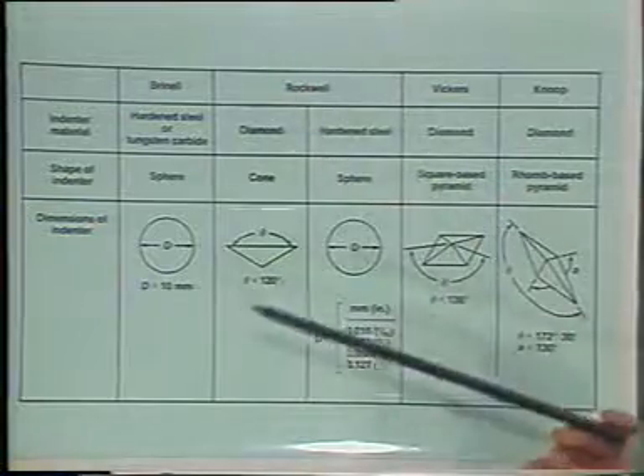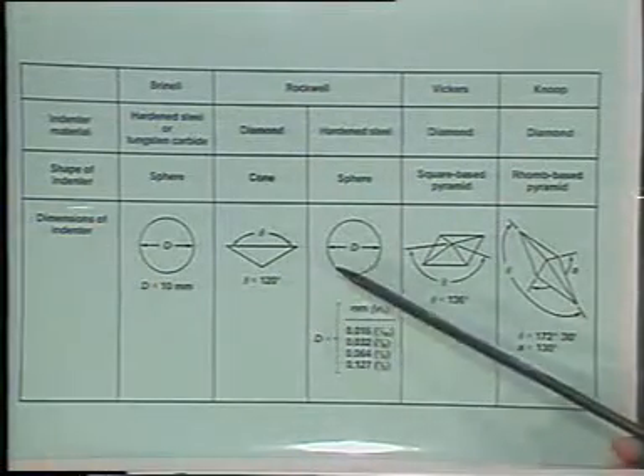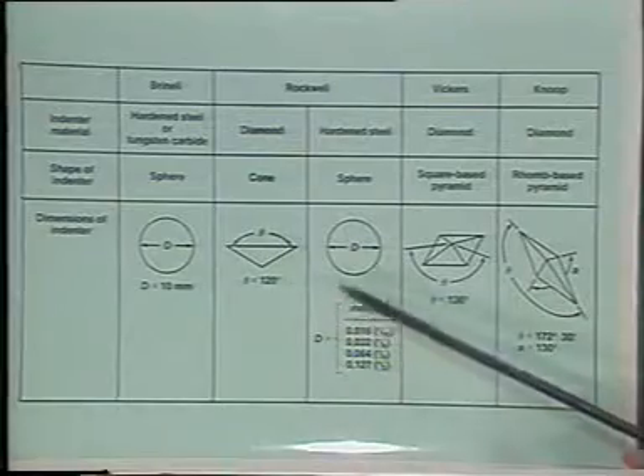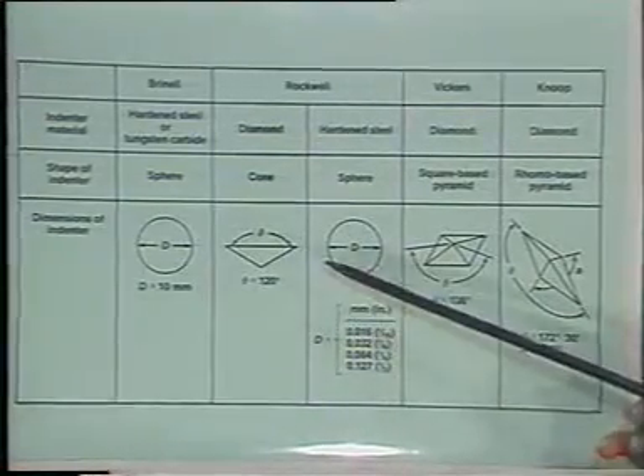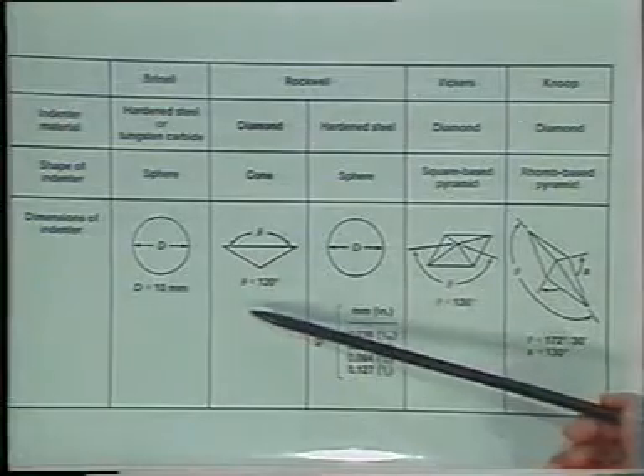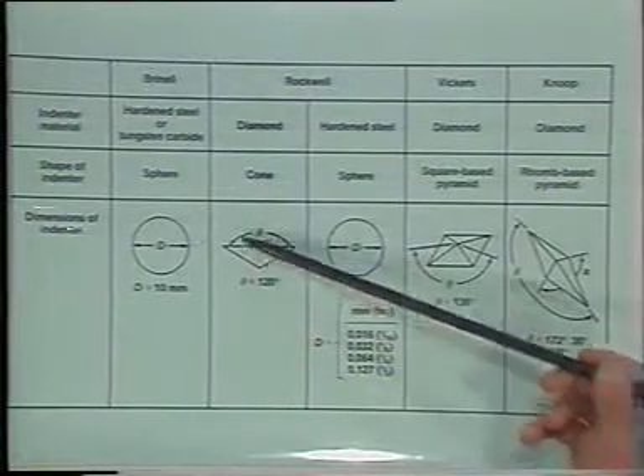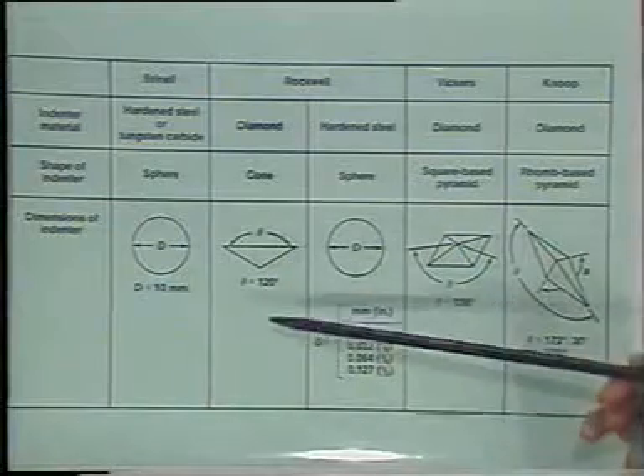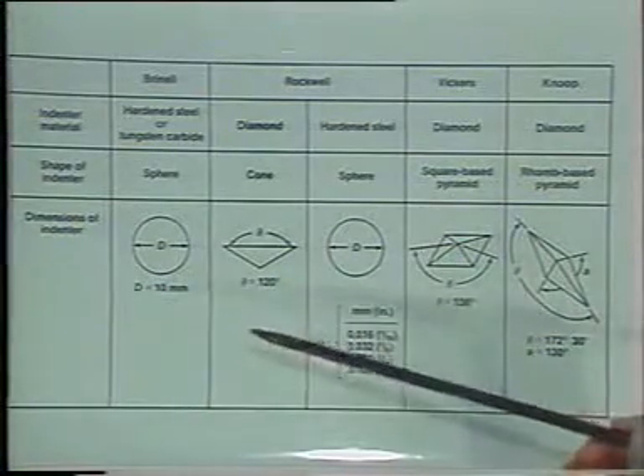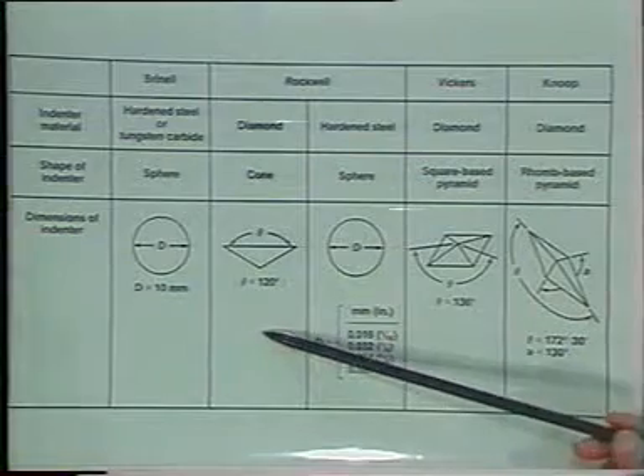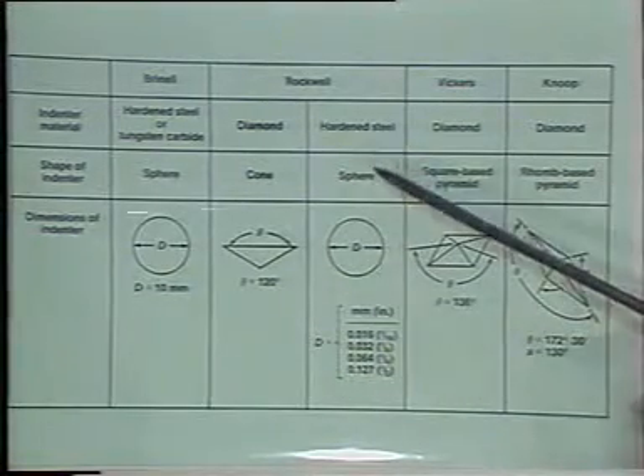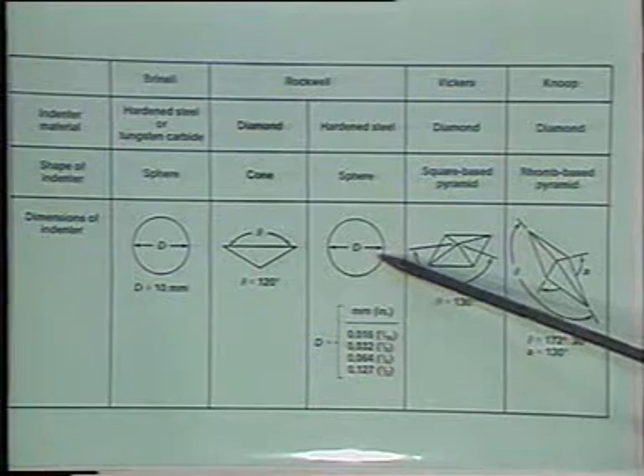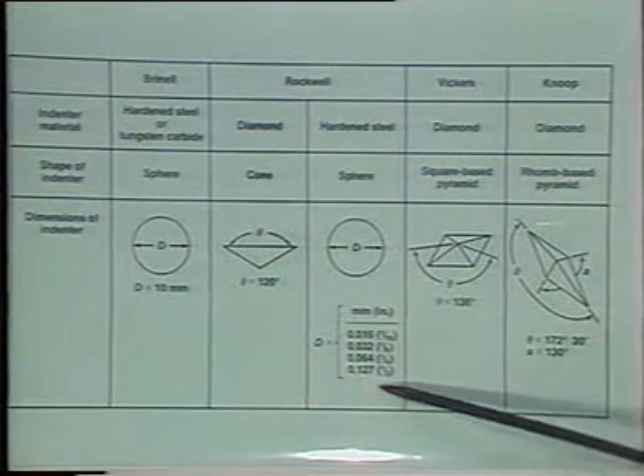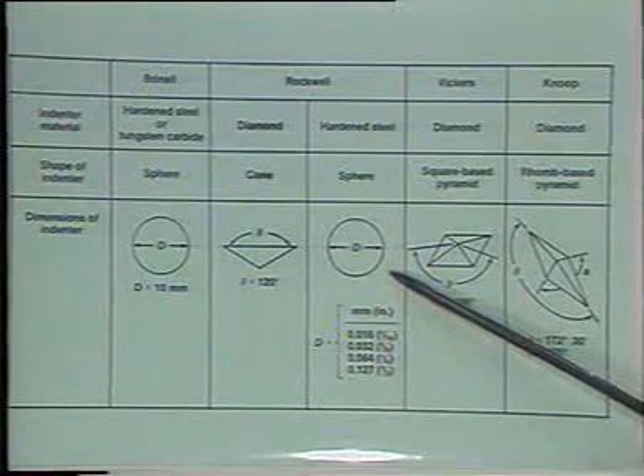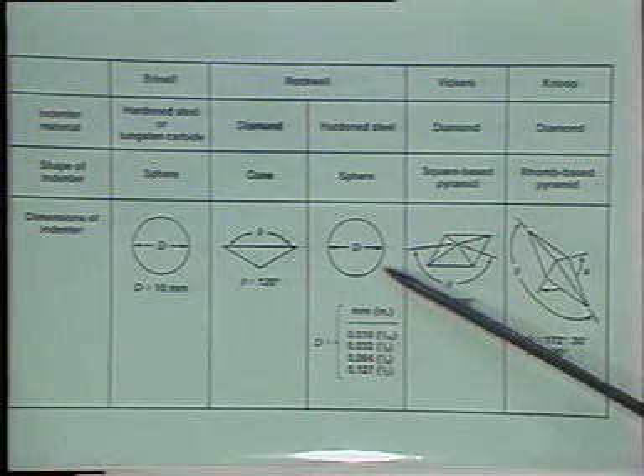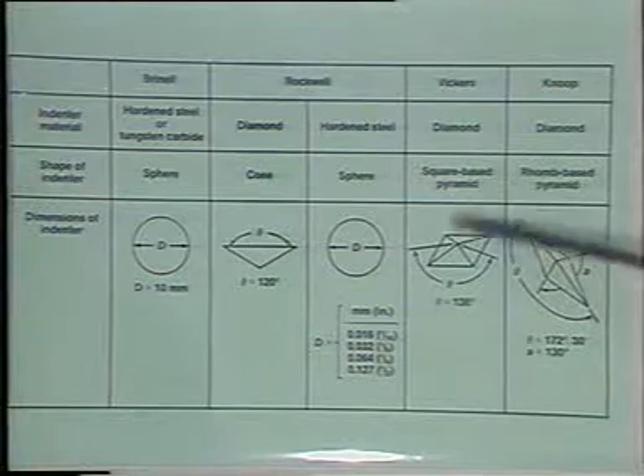In the Rockwell hardness test, we also use penetrators of two types. In one type, we use a diamond cone. It's called a Rockwell C hardness number. And in this particular case, we have a 120-degree diamond cone. We push it in the material, but we directly measure the degree of penetration, and we get a relative number, so we can compare one material with another material. We also use an indenter that's a hardened steel sphere, a 16th of an inch in diameter, or varying in size, depending on what we want to measure. And we do an impression, and again, we get the depth of the impression, so it is a direct reading device.